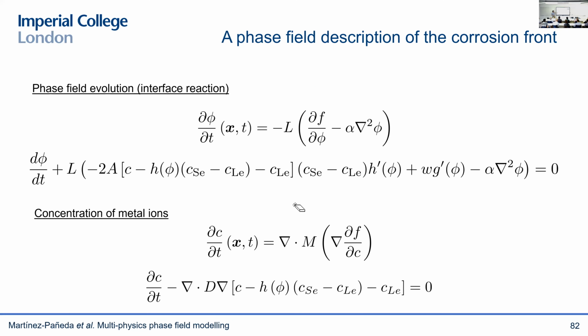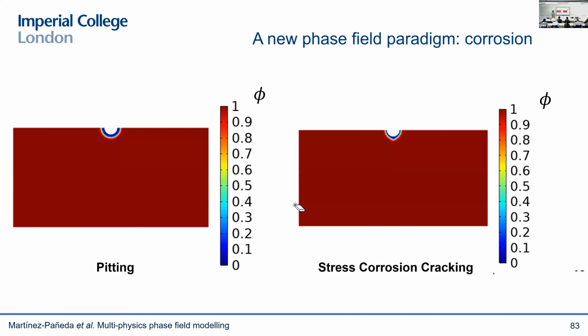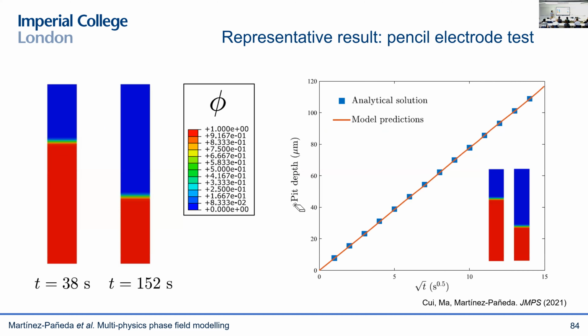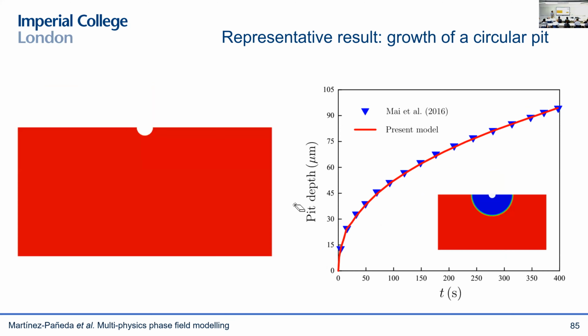And then you have another one that deals with the long-range interaction. So what happens with those metal ions that are detaching from the metal? Where are they going? The transport of those metal ions. So you have these two equations that you're solving for. And when you're solving that, there's also a lot of mechanics that we'll discuss later, but we can show that computationally, suddenly, you're able to capture pitting and stress corrosion cracking. And just to show you some representative results, there's some simple 1D problems that you can use to confirm that your model predicts the same as the analytical predictions. You can see that we get a very good agreement here.